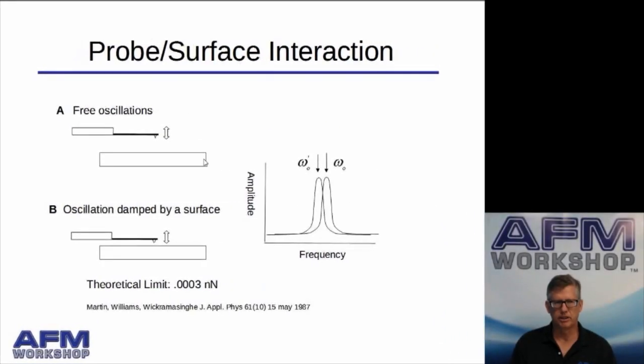So vibrating mode is more sensitive. And in vibrating mode, what happens, of course, is that you have a free oscillation of the probe. And as the oscillating probe approaches the surface, the vibrations or oscillations are dampened by the interactions between the probe and the surface. And then when that happens, you have two things that occur. One is you have a change in the frequency, and you also have a decrease in the amplitude at that particular frequency.